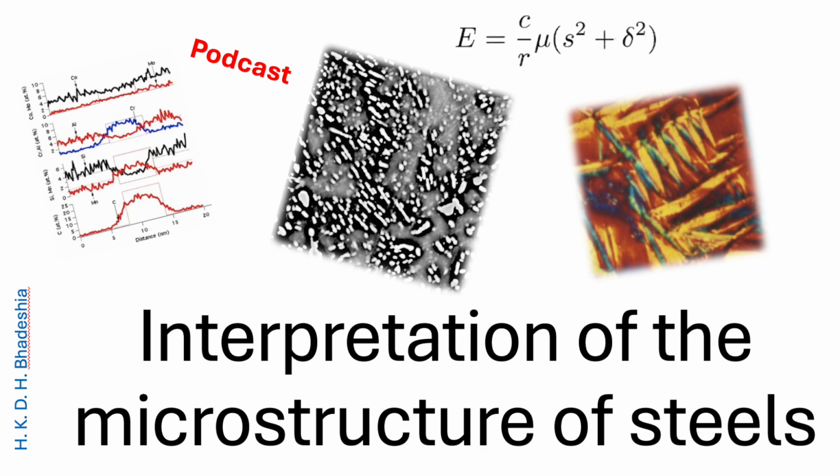Ah. And that's your first major visual rule. Plate shapes scream displacement and high strain. So the key visual takeaway is that simple. Plates mean high strain, no diffusion, and blobby, more complex shapes mean low strain and lots of diffusion. That's the fundamental differentiator. It's a phenomenal conceptual shortcut.